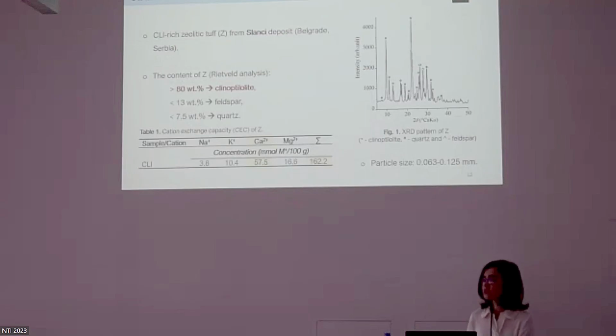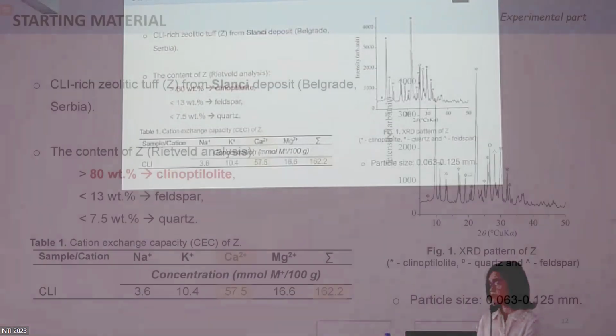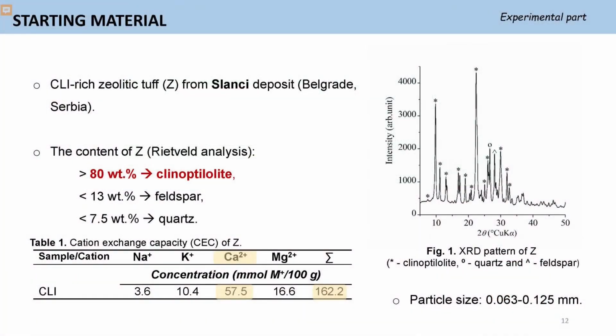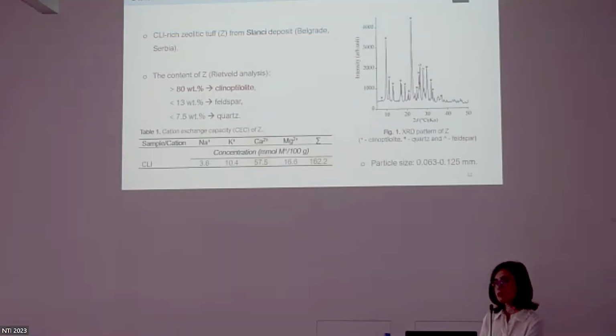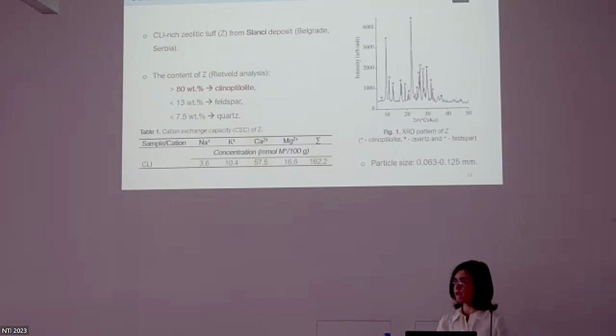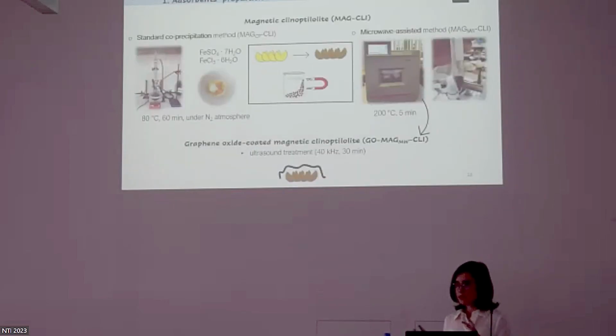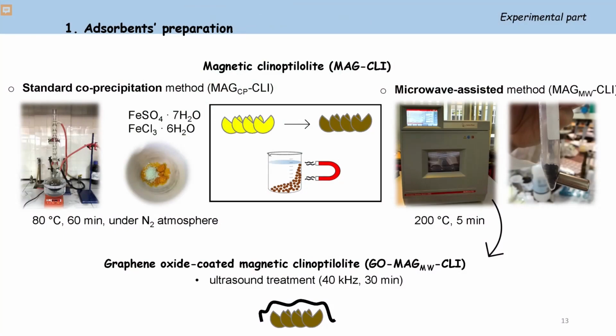So the clinoptilolite-rich zeolitic tuff from the Serbian deposit Slanci was used as a starting material. According to the quantitative analysis, the zeolitic tuff had a high content of clinoptilolite, and feldspar and quartz as satellite phases. Also, the clinoptilolite has relatively high cation exchange capacity, and the used particle size range was up to 125 microns. First, the magnetic clinoptilolite was prepared by 2 different approaches, the standard co-precipitation method and the microwave-assisted method. Then, subsequently, the magnetic clinoptilolite obtained by the microwave-assisted method was coated with graphene oxide using ultrasound treatment.